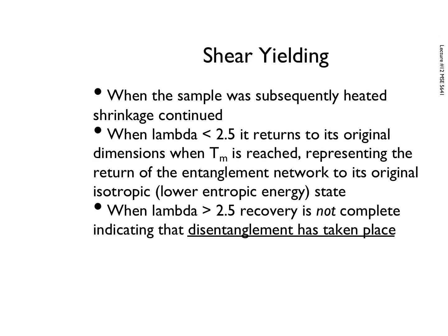So what's happening in this context, when the sample is heated, shrinkage continues. When lambda is less than 2.5 or 250%, it returns to its original dimensions when we reach the melting point, representing the return of the entanglement network to its original isotropic, lower entropic energy state. When lambda is greater than 250%, recovery is not complete, indicating that some disentanglement has taken place. All right, so you've pulled polymer chains out from each other, probably because of some of the higher energies that are involved in these systems. And so that's going to give you a system that doesn't come all the way back to where it used to be.